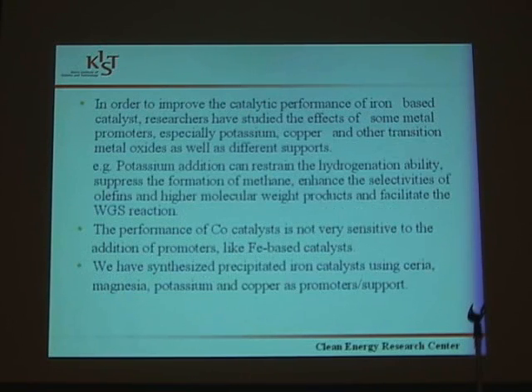In order to improve the catalytic performance of iron-based catalysts, researchers have studied the effects of some metal promoters, especially potassium, copper, and other transition metal oxides, as well as different supports. For example, potassium addition can restrain the hydrogenation ability, suppress the formation of methane, enhance the selectivities of olefins and high molecular weight products, and facilitate the water gas shift reaction.